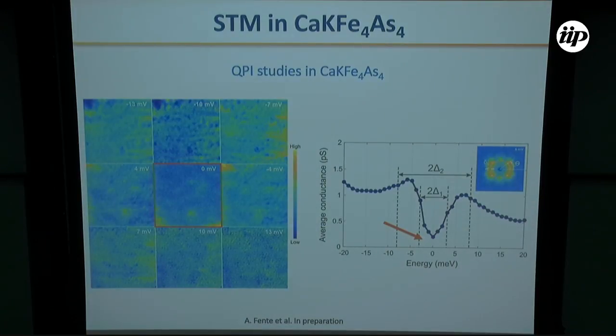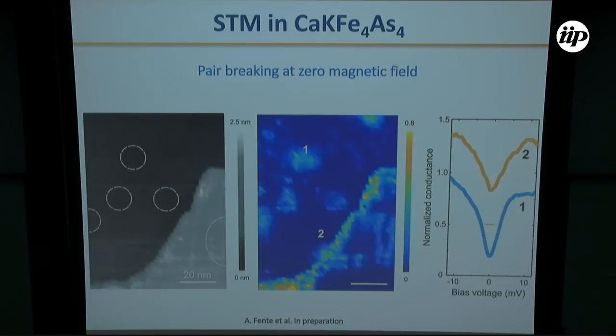Going back to the fact that this signal is non-zero at zero energy, the reason why is easy to see when we look at the conductance maps at the Fermi level. We see that the conductance, the density of states, is not zero in every place. We find some places where the conductance is different from zero. And we understand why when we look at regions with a relatively large amount of disorder.